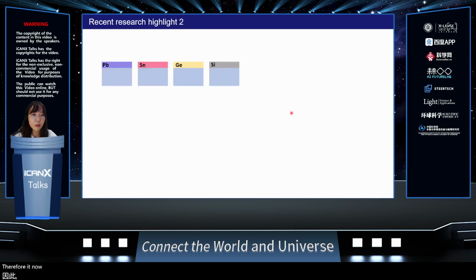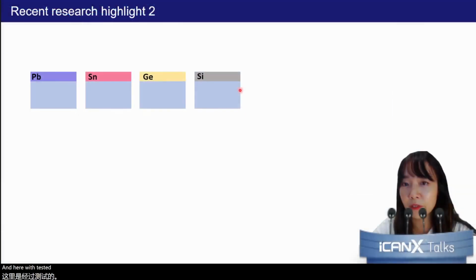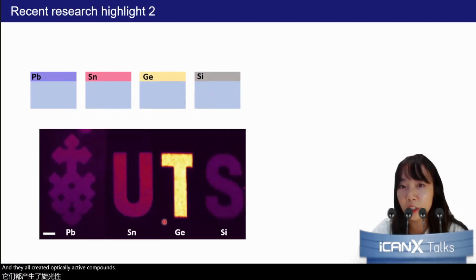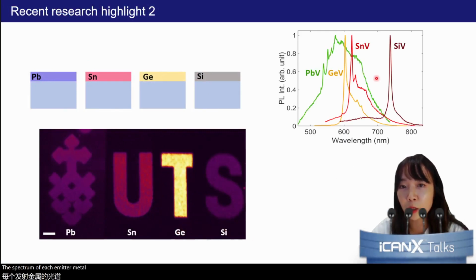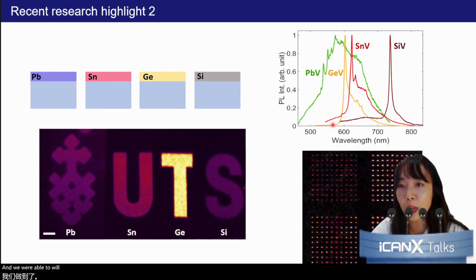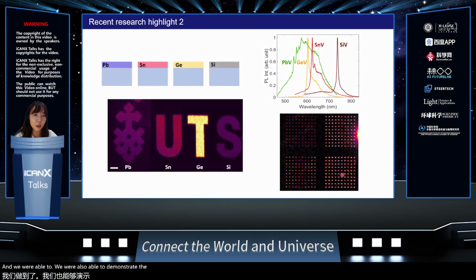Therefore, now any research group that has focused ion beam in the lab can create color centers in diamond. And also by just changing the film material by deposition, you can create various emitters in the substrate. And here we tested 4 different film materials, and they all created optically active color centers as shown in this image. And the spectrum of each emitter matches the known spectrum shapes in previous literatures, and we were also able to demonstrate the emitters in an array.